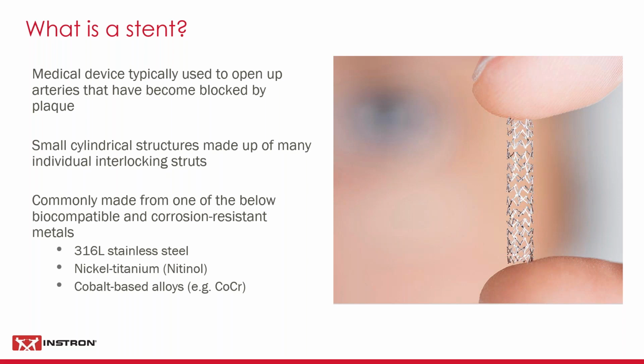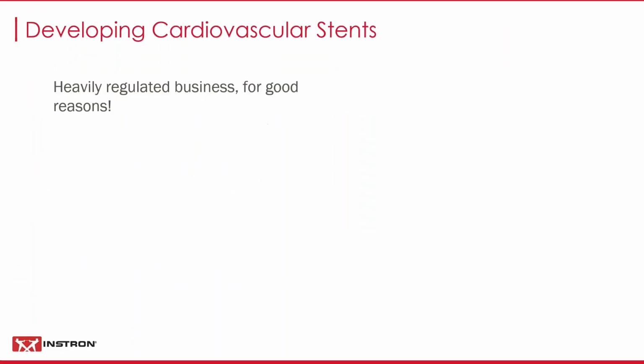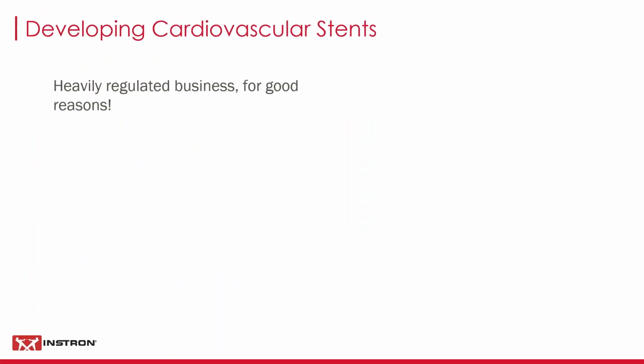Because while all of these alloys have elements in them which, if they were dissolved as salts, would be really quite unpleasant in a biological sense, what happens here is that you form a very thin, very stable oxide or passivated layer, and that protects the metal from dissolution, and that stable layer keeps everything as it should be. It doesn't dissolve, and no unpleasant toxicity effects happen, at least if you've done things right.